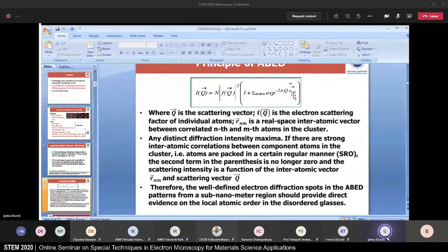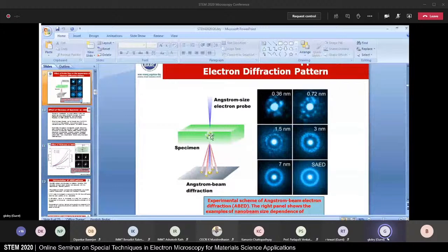Here, the important thing is when you make the beam small, how many atoms are you actually sampling? You can have one cluster, you can have many clusters. If you have many clusters, then all the information from those clusters will get superimposed in your diffraction pattern, and it will be very difficult to interpret. Therefore, it's very important to have a very thin sample, and you should have fewer atoms being examined. This view-graph here shows the effect of the beam size on the appearance of the diffraction pattern.